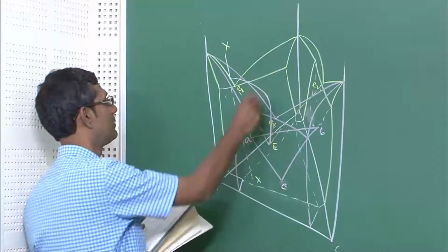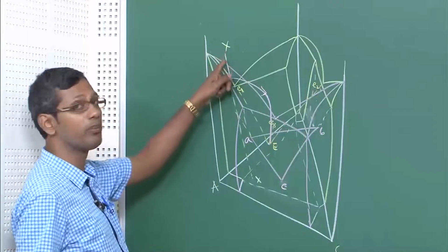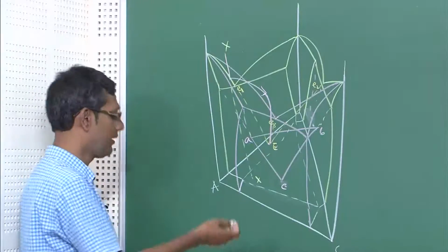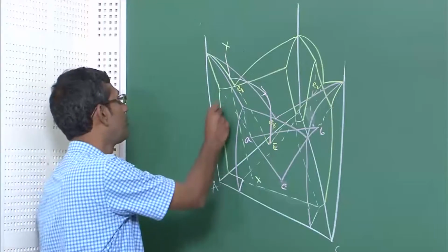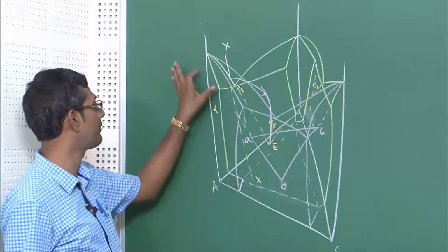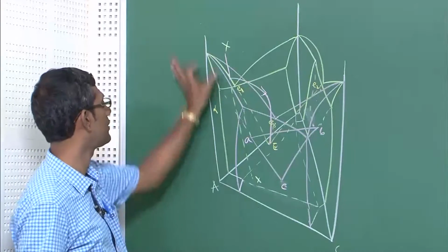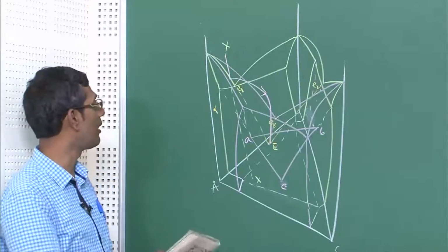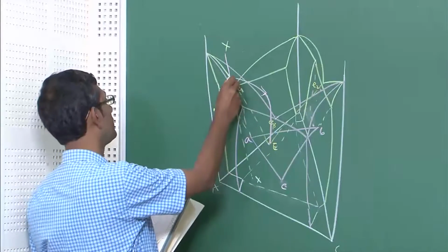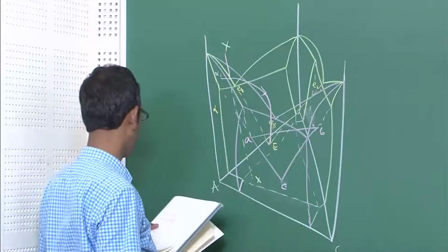What does it mean? This is the track of solidification pathways. What does it mean? This means that as the alloy composition goes down this way, it will start precipitating alpha. Remember, this is alpha, right, alpha phase field. Solution between A and C, or A and B both, this is alpha phase field. If you connect these two, this particular phase field here is alpha. So, it is going to precipitate alpha here, and alpha will have a composition of alpha 1, which you can obtain from that.